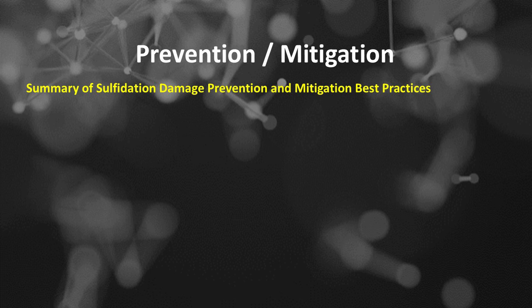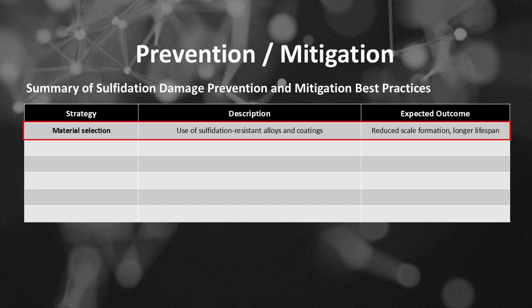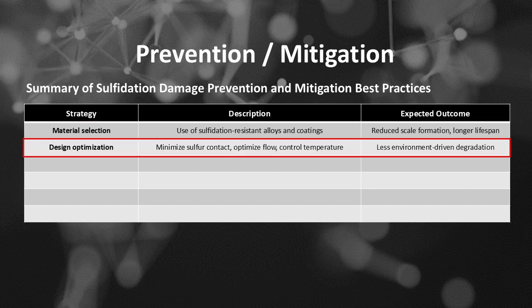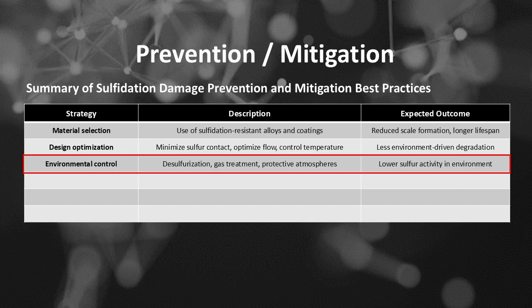Summary of sulfidation damage prevention and mitigation best practices. If prevention and mitigation strategy is material selection, described as use of sulfidation-resistant alloys and coatings, then the expected outcome is reduced scale formation, longer lifespan. If strategy is design optimization, described as minimize sulfur contact, optimize flow, control temperature, then the expected outcome is less environment-driven degradation. If strategy is environmental control, described as desulfurization, gas treatment, protective atmospheres, then the expected outcome is lower sulfur activity in environment.